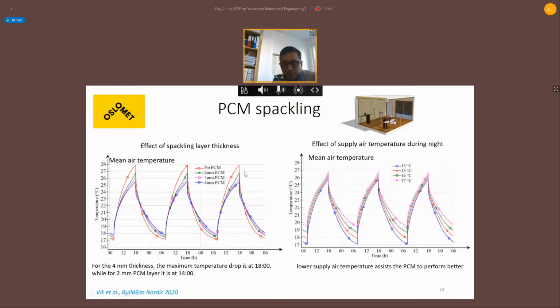Also here you see in the night time, the temperature, which in our base case was 14 degrees. If we keep on increasing it, it's not suitable after a certain temperature because the PCM is not properly recharged in those cases. So naturally we have a reduction of temperature which is less in time when we have a higher nighttime supply temperature. So ventilation is also important for nighttime charging.